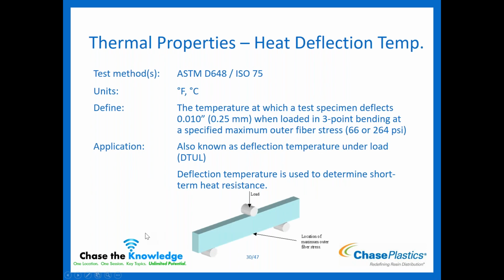So now we'll start talking about some thermal properties, starting with heat deflection temperature. The real scientific term for it: it's when it deflects 10 thou of an inch when it's loaded in 3-point bending at a specific outer fiber stress. So you'll see on a data sheet there are generally 2 different conditions, either 66 PSI or 264 PSI, also known as 0.45 MPa or 1.8 MPa. So the different loadings are the different conditions for this particular test. This is also known as deflection temperature under load. So if you see DTUL referenced somewhere, just note it's the same test, just with an updated name. And then deflection temperature is a really good indicator of short-term heat resistance.